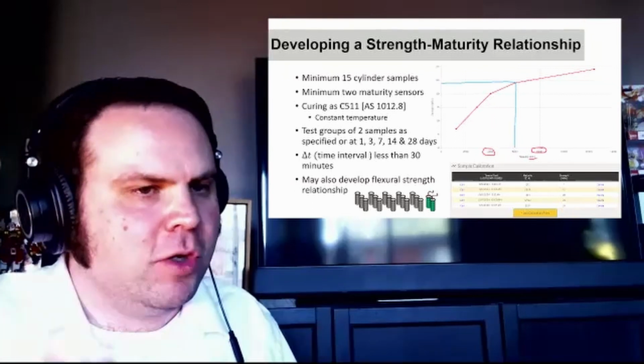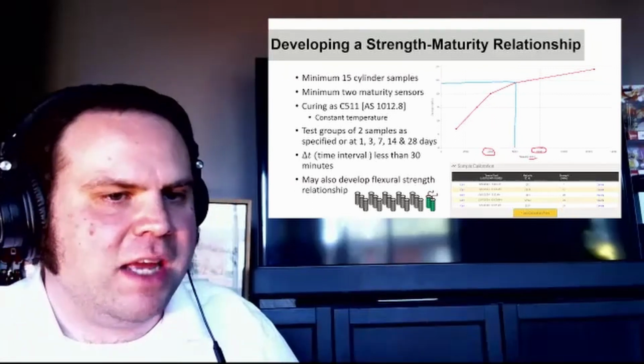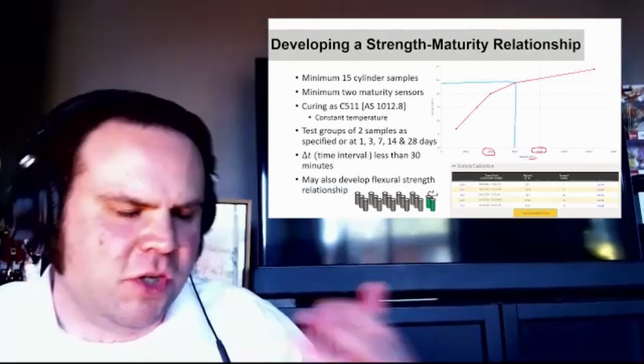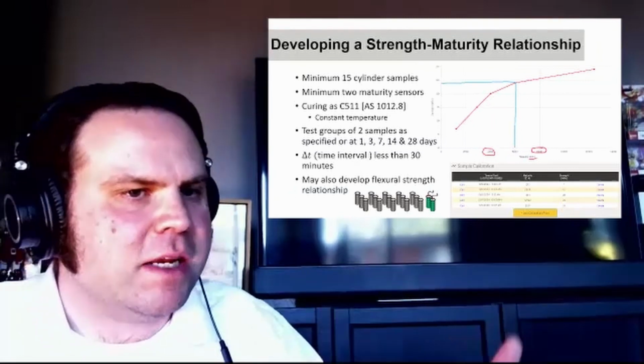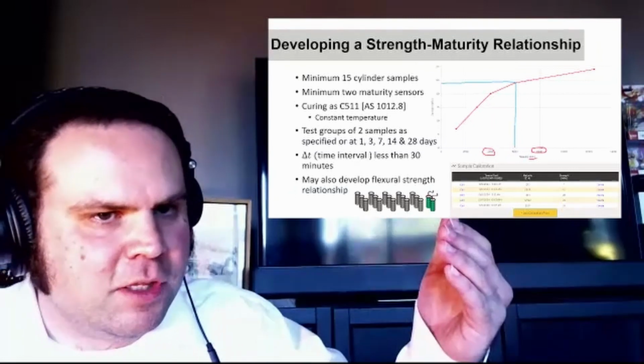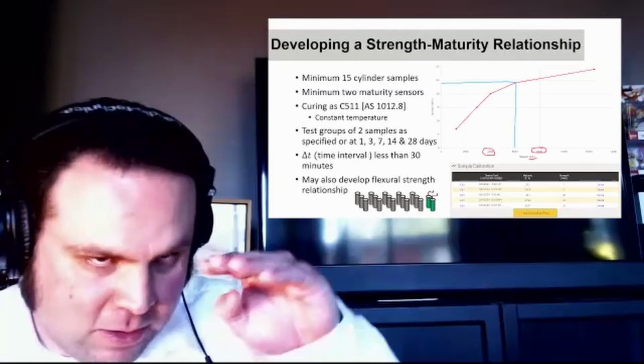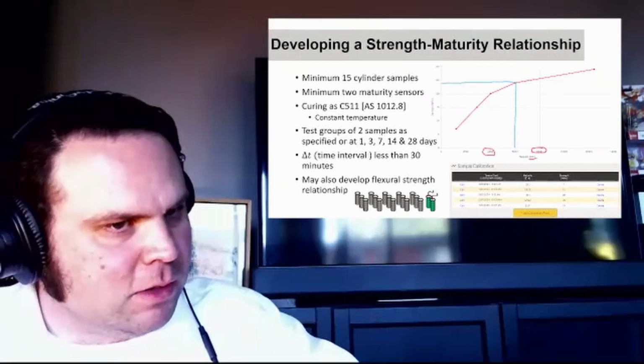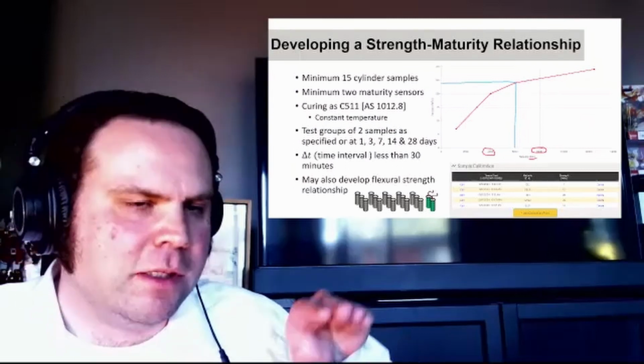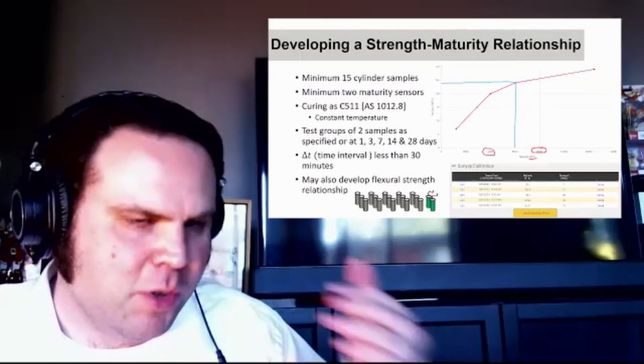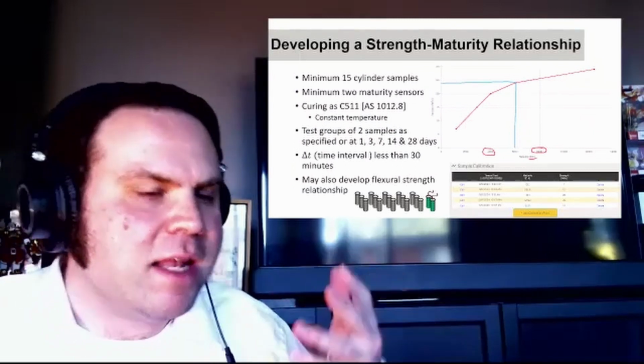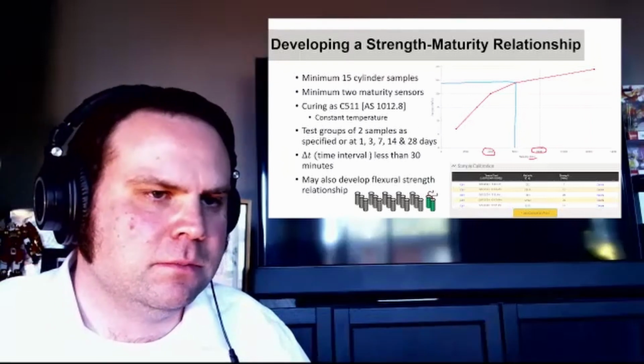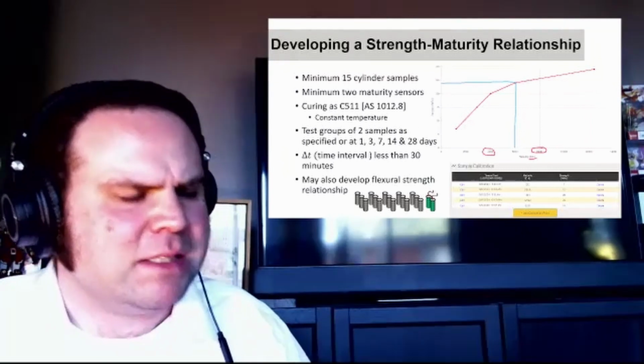So if you look at the MPa at your 7-day mark on your 7-day crushers, that'll have a high maturity index, and your lower in situ concrete will have a lower maturity index on the same day. So it'll catch that it hasn't gained as much strength. That's the purpose of this exercise. Okay, gotcha. Does that clarify?